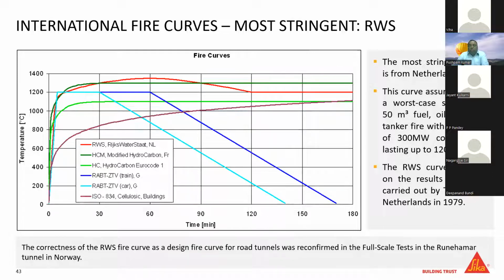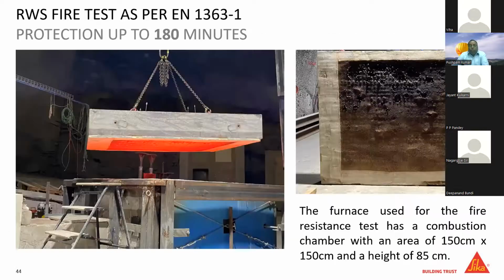This test was done for a fire curve of 1200 °C. Like the fire would be at 1200 °C, and therein the performance of the mortar would be tested. So you can see the test specimens on the furnace: the concrete block with fire protection mortar is exposed to fire, and this mortar is tested at regular intervals. This is a 1.5 meter by 1.5 meter section which is exposed to fire, and the fire rating is tested.